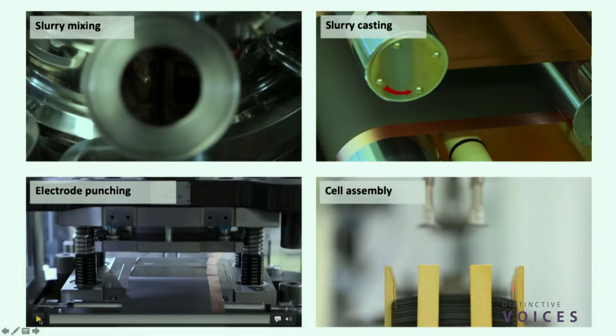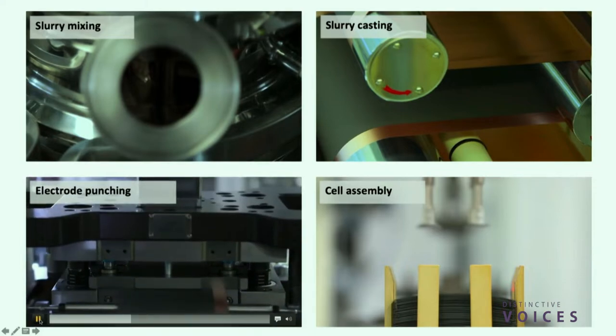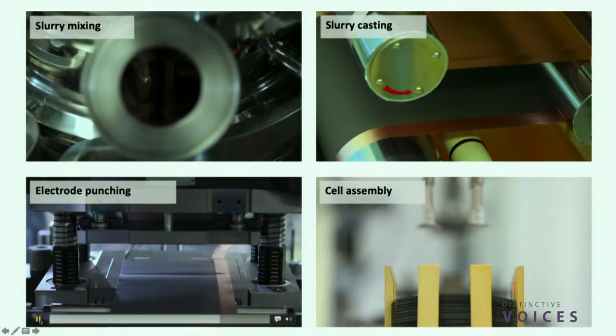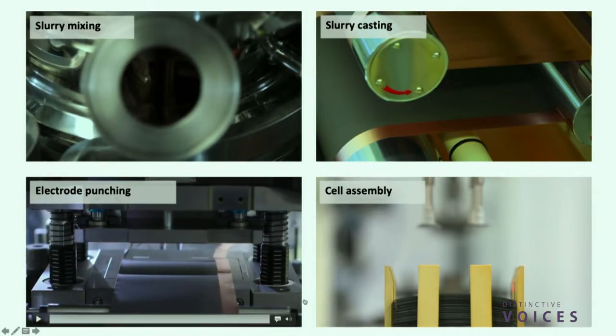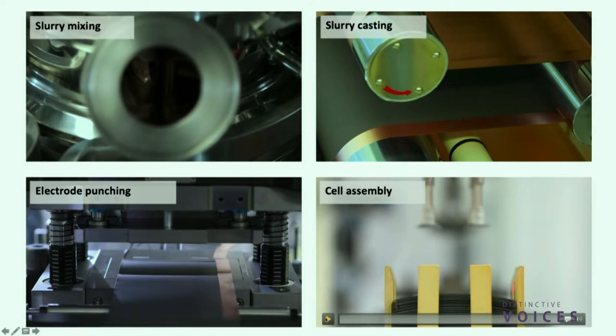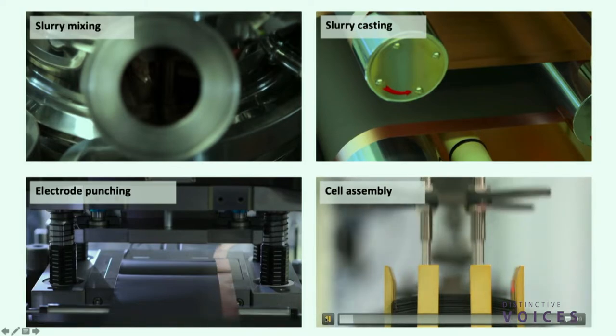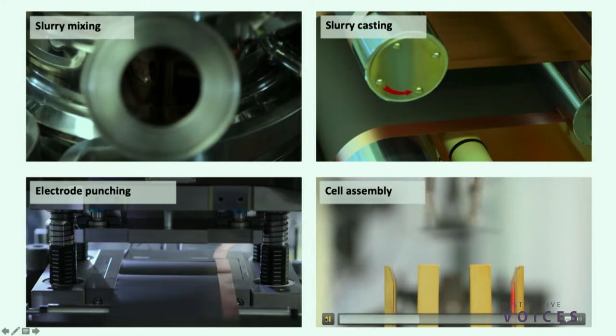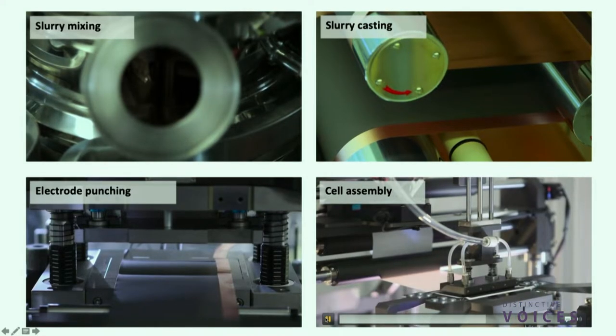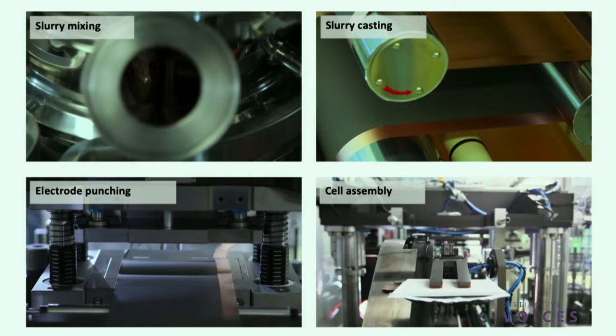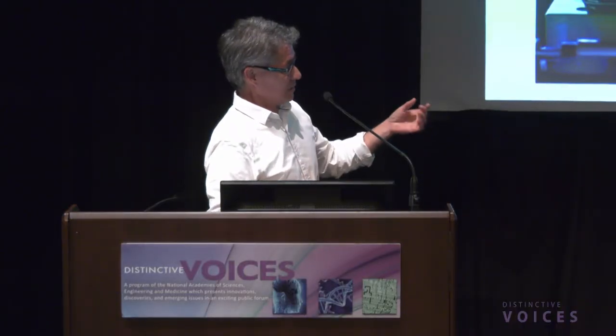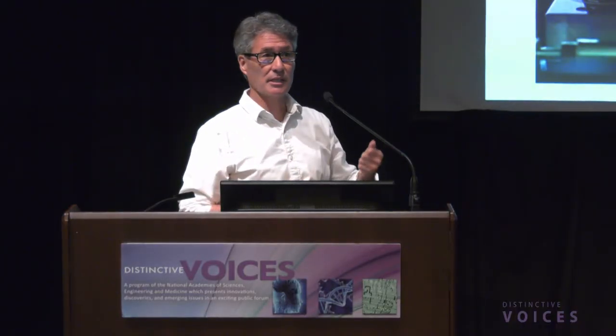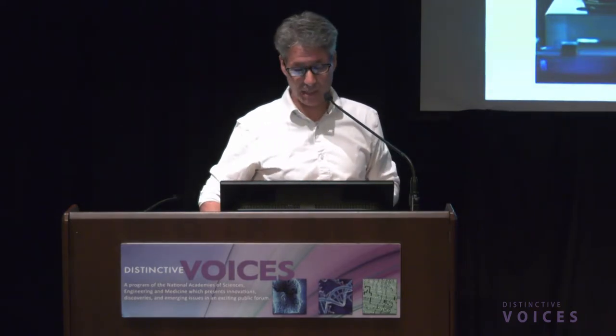And then once you have that electrode, you punch it. If it's a pouch cell, you punch out squares. Once you have those squares, anode square, cathode square, or rectangles, separator, then you can use robots. There are very few people. I mean, these manufacturing facilities are automated. This is a Z stacker. It's stacking all the cathodes. It folds in the separator, welds the tabs, and that's basically the lithium-ion cell. Put it into a pouch, fill it with liquid electrolyte, and seal it up. And that's essentially how batteries are made.